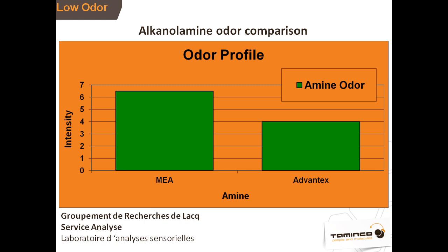miraculous about this. One can do the same thing just by opening the bottle and smelling it, but there are quite a few things that happen when you do comparative odor analysis. You have to be careful not to compare aqueous solutions to pure materials. If you have an 80% aqueous solution of one material and you have a neat sample of the other material, you should dilute the neat material to 80% before you do a comparative odor analysis, because the partial vapor pressure of the water can significantly influence the way your nose interprets the odor.